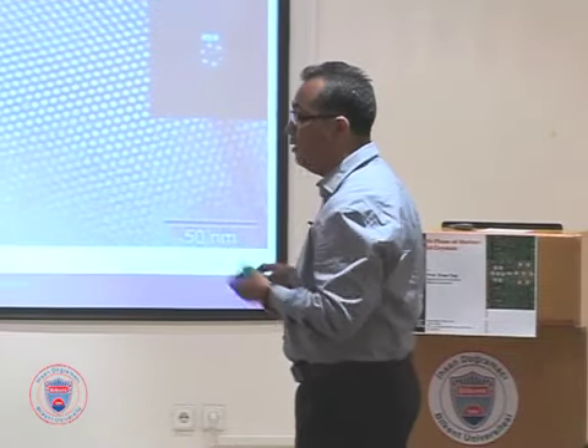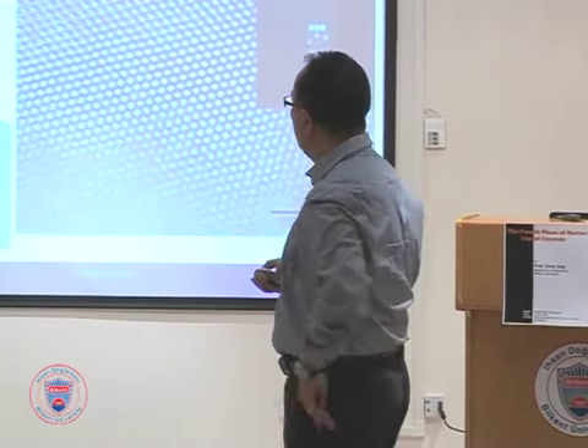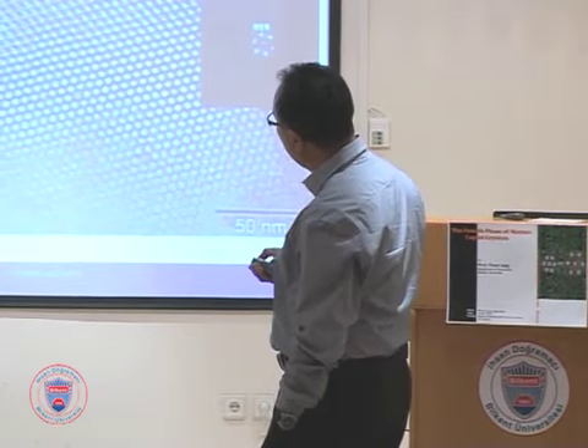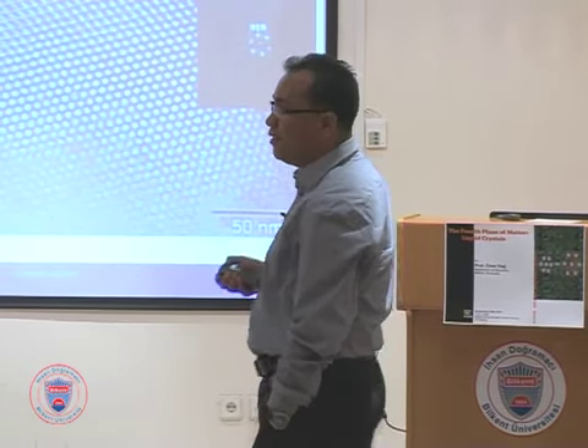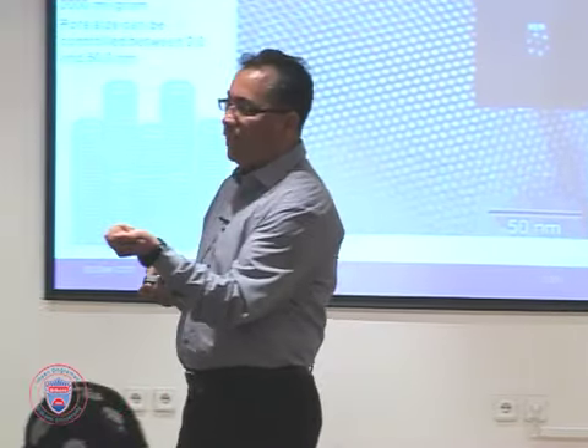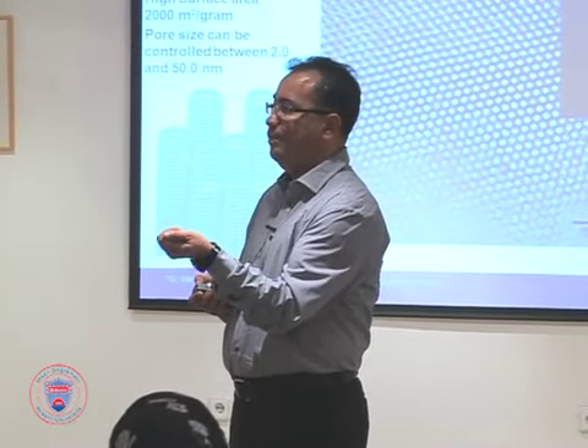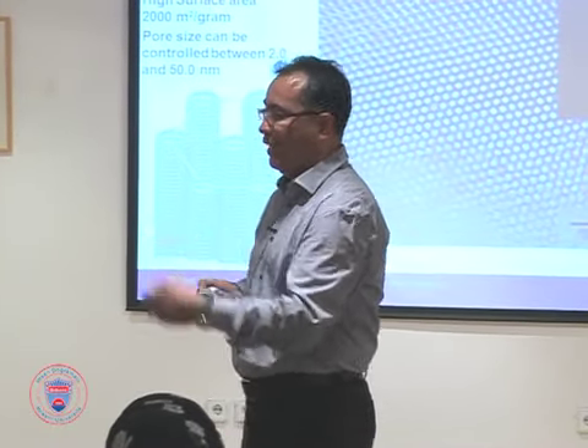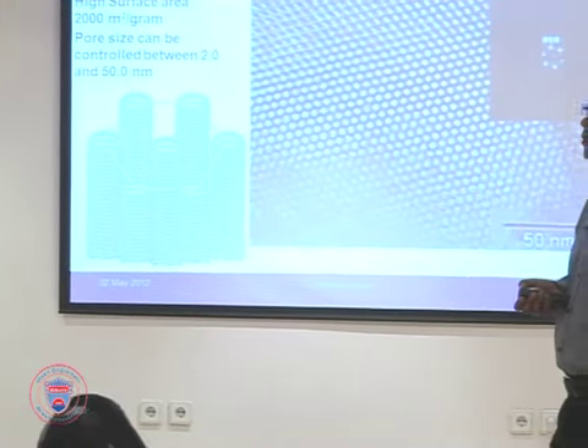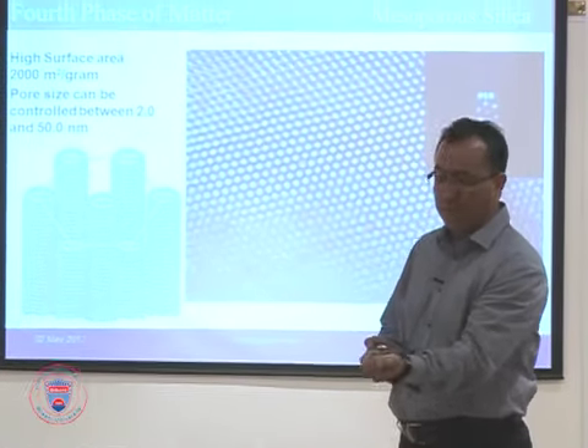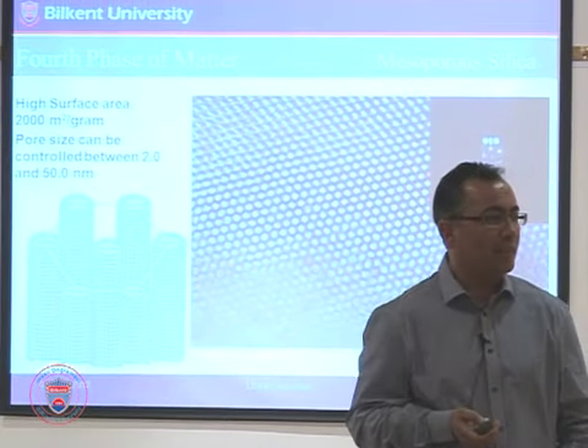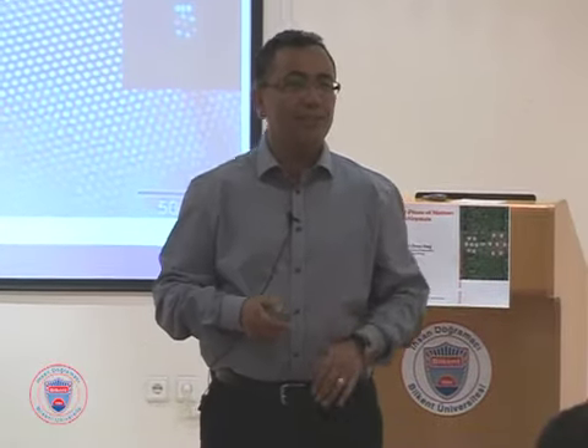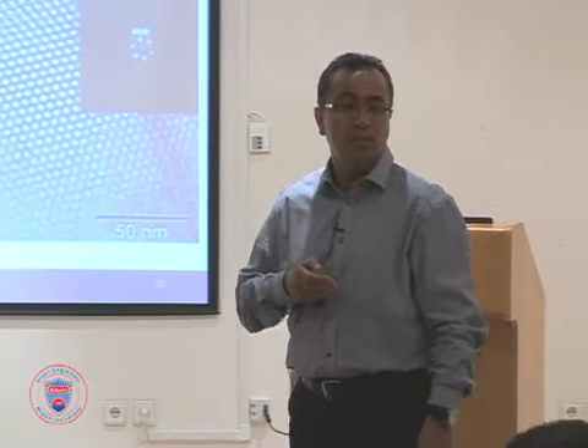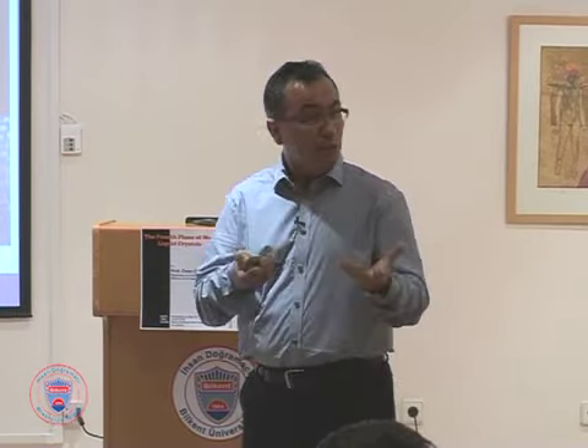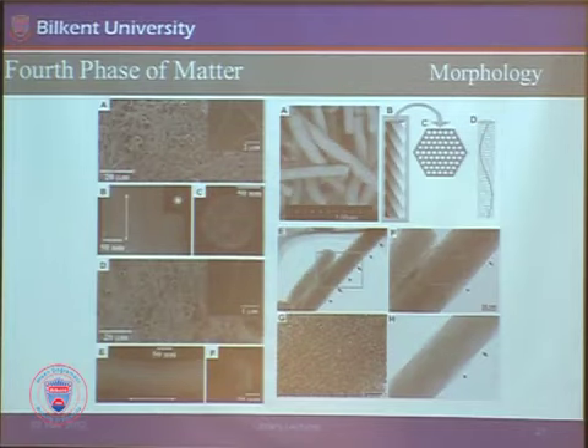You can modify the surface, you end up with a very, very large surface area. Look at this number. You have 1 gram of glass. 1 gram of glass probably has a few square centimeters of area in the regular way. But here you have 2,000 square meters. Almost like a soccer field. In a very tiny powder, you have a field inside that you can modify the surface to make catalysis, to make many applications basically, and use this surface for something. Okay?